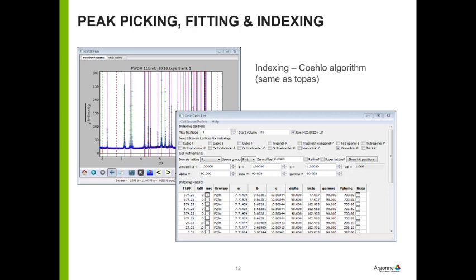For solving crystal structures, the process first involves indexing the pattern, finding out what unit cell belongs to that pattern. And by the way, you don't do this on a mixture. You really need to have a pure material with one set of reflections, because trying to index two overlapping patterns is damn near impossible compared to doing a single one.